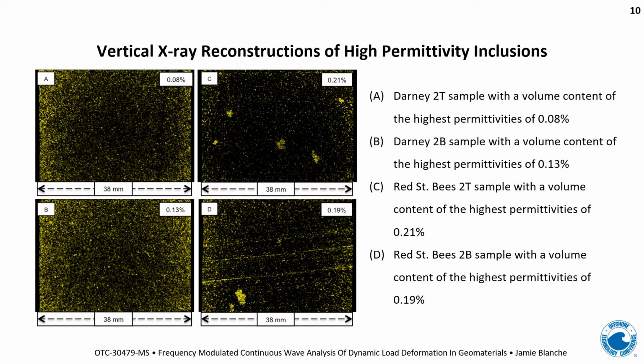The Darney 2B sample, B stands for bottom, T stands for top, has a volume content of the highest permittivities of about 0.13%. The Red St. Bees top sample has a volume content of 0.21% metals. And the Red St. Bees 2B sample has a volume content of metals of approximately 0.19%.